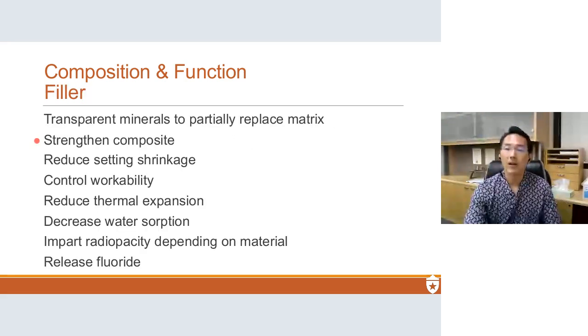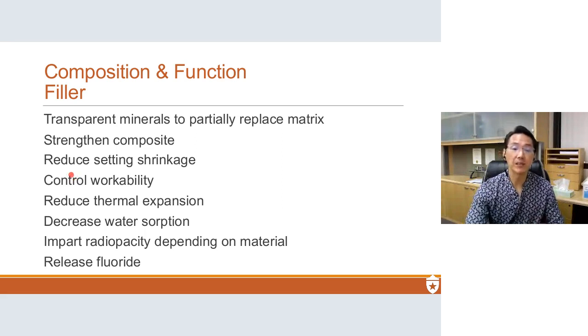Now, the filler is the second component. And basically, these are glass particles, mineral glass particles. And they're used to replace the monomer. Okay? The glass particles are stronger than the polymer, so they will strengthen the composite. Since the glass particles themselves don't react, they reduce the number of reactions, and so they reduce setting shrinkage. They control the workability because I told you these are kind of sticky. When you fill it with glass particles, it becomes very pasty and less sticky.